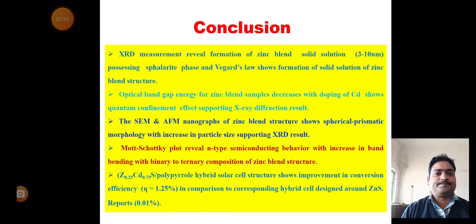Zinc cadmium sulfide polypyrrole based hybrid solar cell structure shows improvement in conversion efficiency. Eta is equal to 1.25% in comparison to the corresponding hybrid cell designed around zinc sulfide, which was earlier reported as 0.01%.